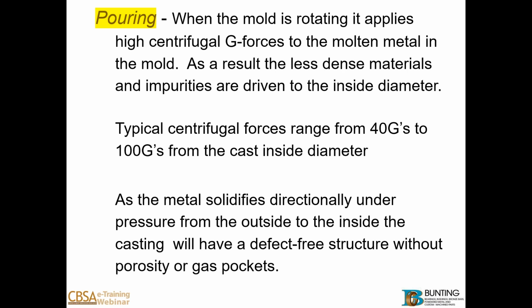As metal solidifies directionally under pressure from the outside to the inside, the castings will have a defect-free structure without porosity or gas pockets. That's obviously the goal. I will tell you that's not 100%, and that's why we semi-finish these things on occasion. It is not always a perfect science, but if we follow the rules, generally speaking, we make some really good alloy.